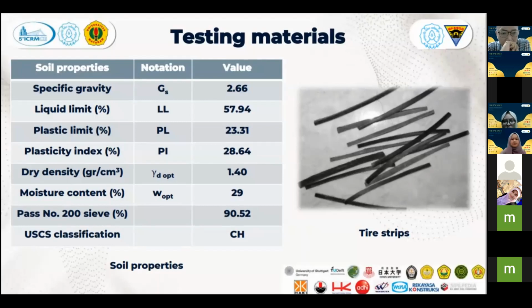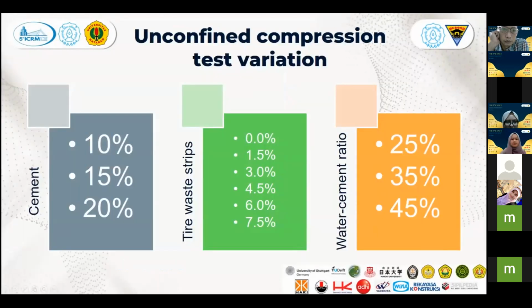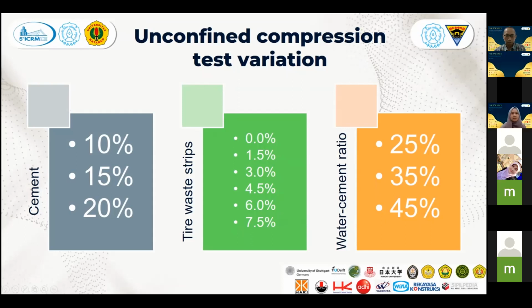The reinforcement materials used in this test are cement, tire waste, and water cement ratio for the hydration process. Tire waste has been cut in 1 mm times 1 mm times 30 mm dimension and mixed with soil, cement, and water in various weight conditions. The weight of tire waste varied from 0 to 7.5% of dry weight of the soil mixture. The water cement ratios used in this study are 25%, 35%, and 45% of the cement dry weight. Due to variation of the mixture composition, a wide range of data is obtained. The data obtained from the unconfined compression test were then calculated and analyzed using sensitivity analysis.